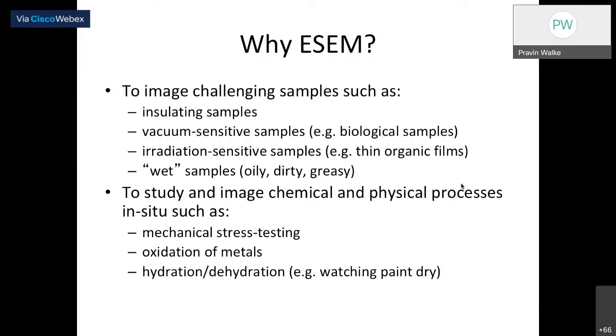Okay, so in the ESEM, what we see is vacuum sensitive samples. For example, there are a lot of biological samples, right? Those biological samples may not survive at very high vacuum. They may not survive, right? And therefore sampling is one issue, and another is imaging, right? So to do biological sample imaging, we need to have the ESEM, right? Or thin organic films, so irradiation sensitive samples. If you bombard electrons, then irradiation happens on the surface. And another important thing is wet samples, for example oily, greasy and dirty samples. In that case also, ESEM will help you to give good imaging, right?